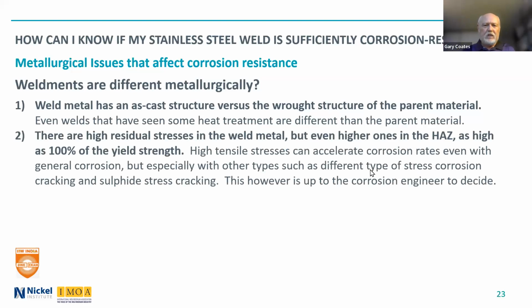There are high residual stresses in the weld metal. As the weld cools from a molten state, it actually shrinks and it pulls the parent material in. You can get high stresses in the heat affected zone, as high as 100% of the yield strength. It actually can go above the yield strength and pull the material, and you can get very high residual stresses there. And this is where you have to be concerned about stress corrosion cracking and sulfide stress cracking.